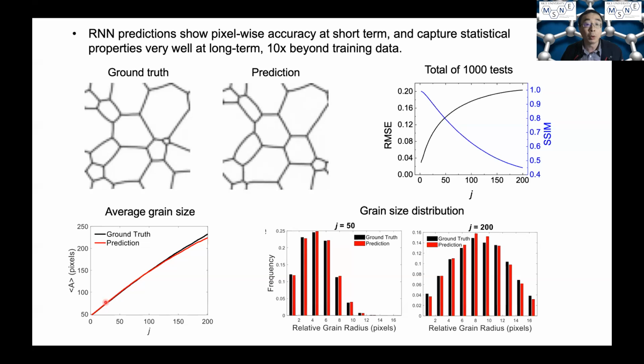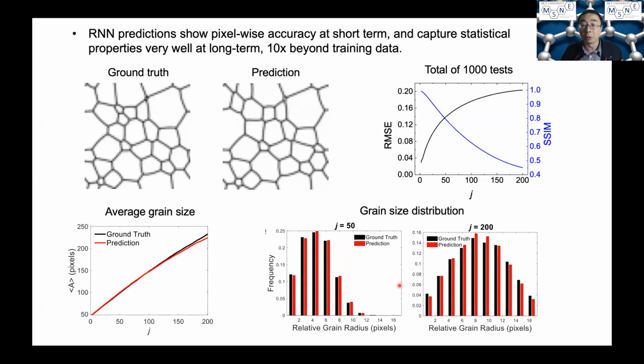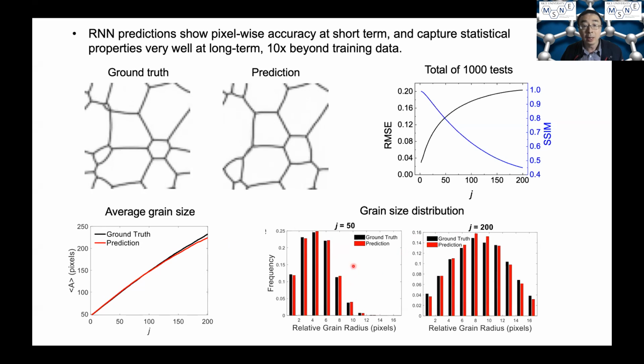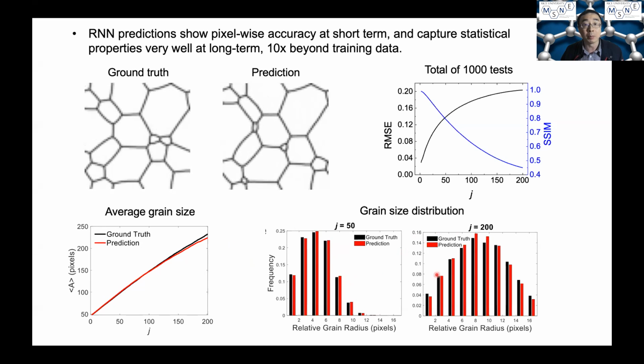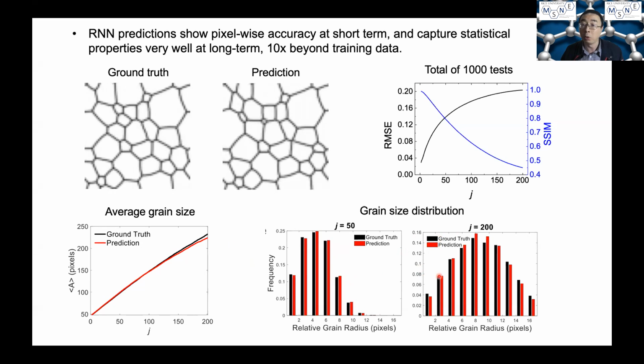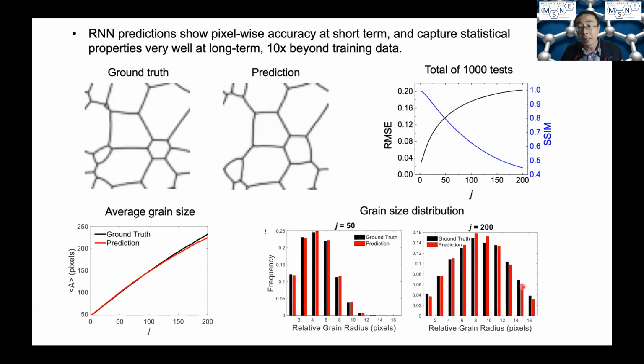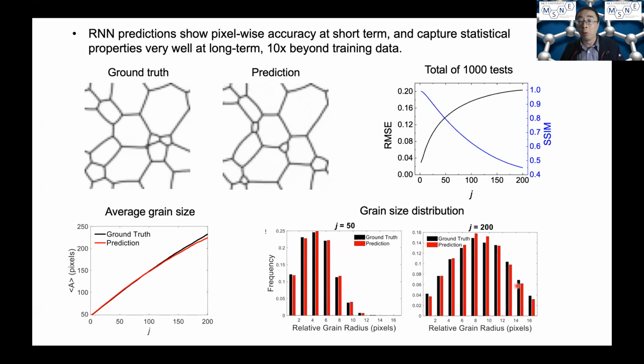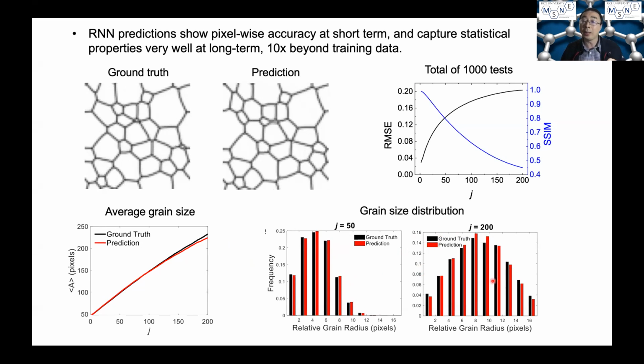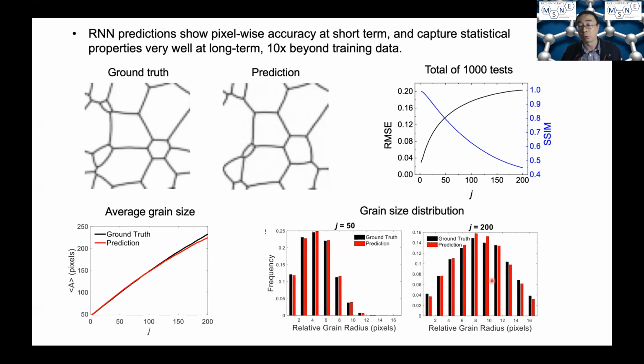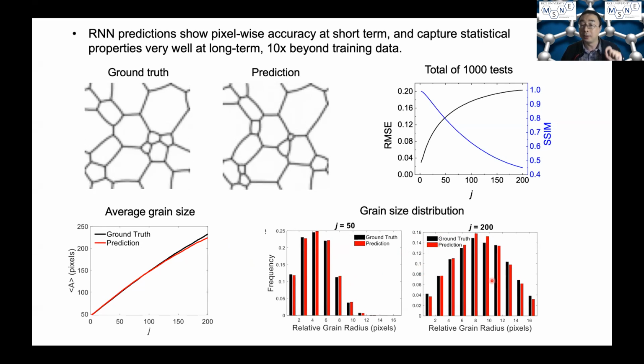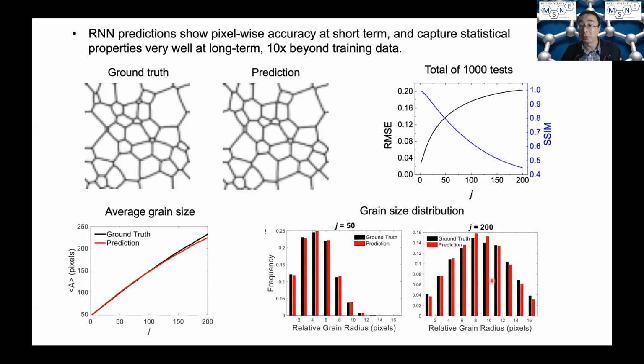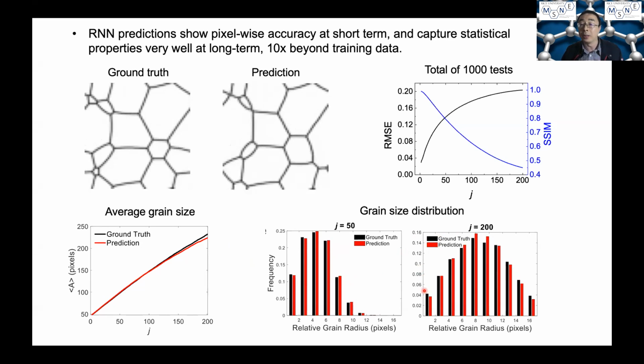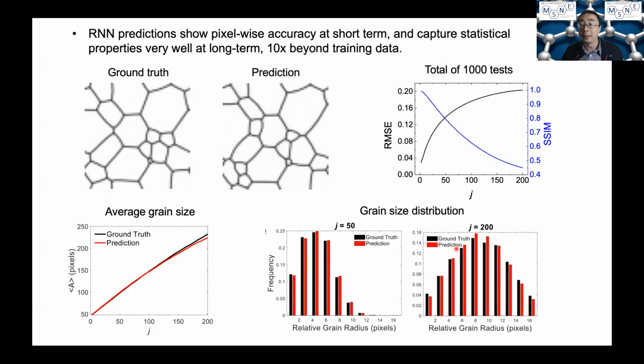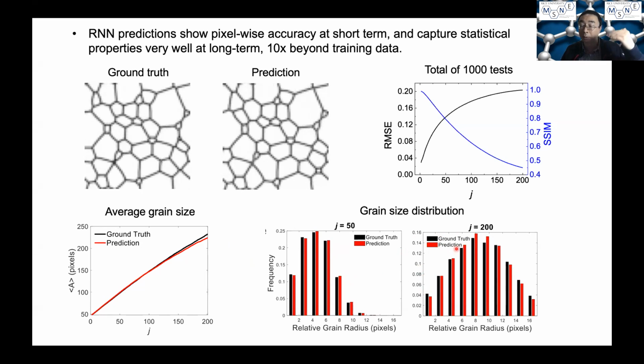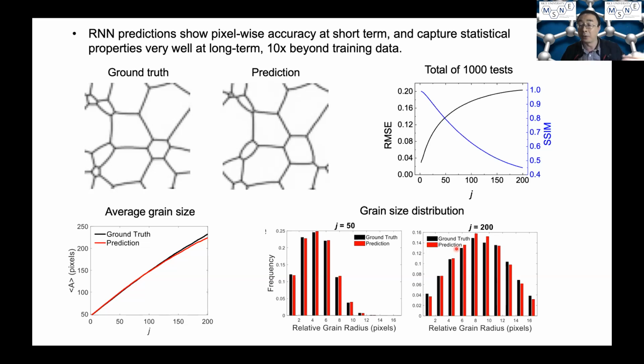So here, for example, we look at the average grain size and also the grain size distribution. We found both of them have very good agreement between the ground truth and predictions towards the end of the simulation. And I think in some sense, this is even more important because in the end, it's the statistical properties of the microstructure rather than individual pixels that controls the performance of materials. So in that sense, I think the RNN model does a very good job in extrapolating the learning in the temporal domain that's well beyond the training data set.